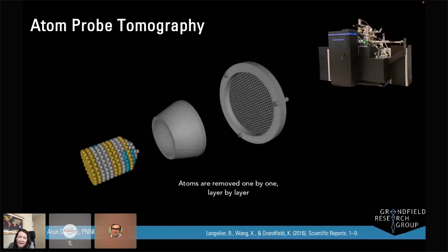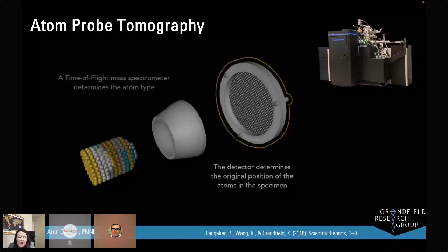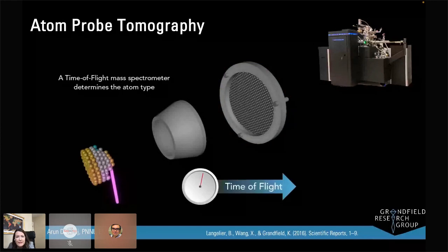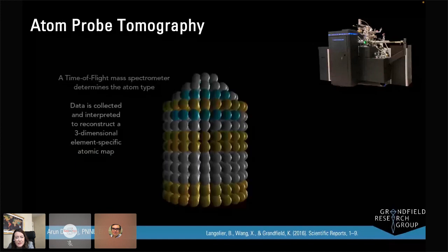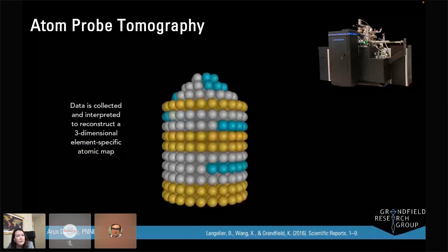In this case, you'll have ions or atoms ionize, and they move towards a position sensitive detector that's also a time of flight detector. We measure the mass to charge ratio of each of these atoms and the time it took for them to hit the detector, and we can create a three-dimensional map of where every atom was in the sample.